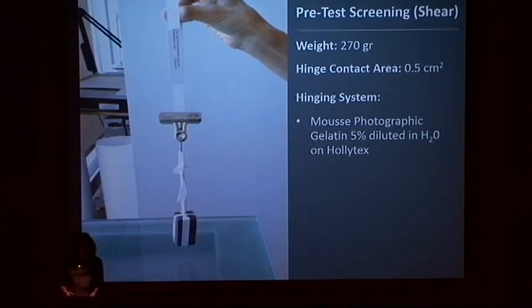This image shows you our shear test, where a hinge with a contact area of 0.5 square centimeter and a load of 270 grams gives the approximation of the shock a photograph in a crate in transit might receive if the crate suddenly drops. Originally, 2% gelatin failed this test, but we repeated this test with gelatin 5% on Holytex, and the hinge remained suspended, and this was quite impressive to us.